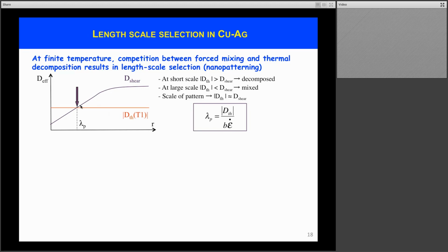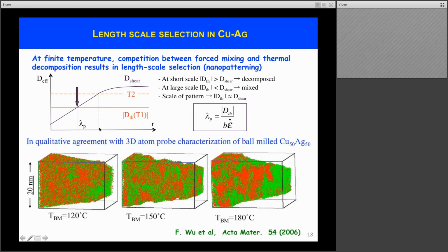And so a natural prediction is that the crossover between these two response curves here is the scale at which the patterns are stable. And so it gives us a guideline as to how the length scale of the patterns would change with diffusion and plastic strain rate. In particular, if I were to increase the temperature from T1 to T2, the red line would move to this dotted red line, and the length scale of the pattern should shift from this value to a larger value.